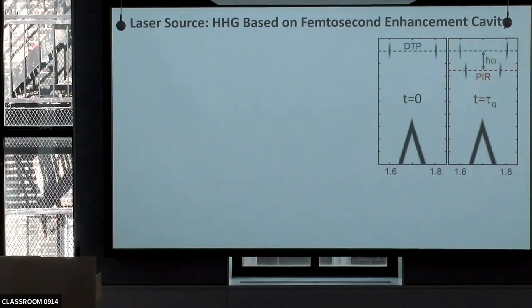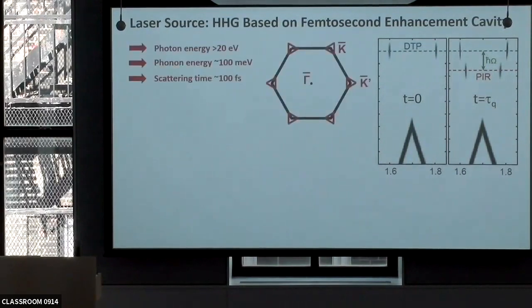What does it take to do that? The experiment looks very trivial, or simple in concept, but what does it take to do that? Well, the problem is graphene, or graphite, they are the same, has a band structure which is located really at the corner of a Brillouin zone. So just to get there kinematically and have enough cross-section, you're looking at photon energy above 20 electron volts. So you can forget about 6 eV lasers.